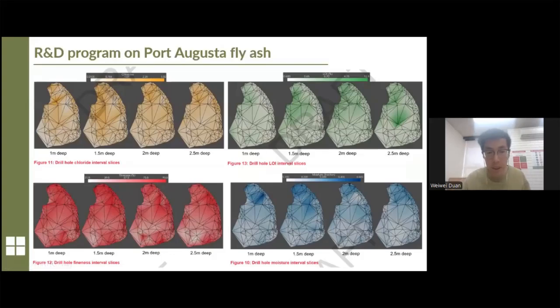And that is the 3D profile we investigated for the specs of chloride, LOI, and fineness, and this one is the moisture. If we first look at the moisture, we found that the north side usually has higher moisture. This is because, remember, the fly ash is pumped from the south side, then flows to the north side. This causes high moisture at the north side.